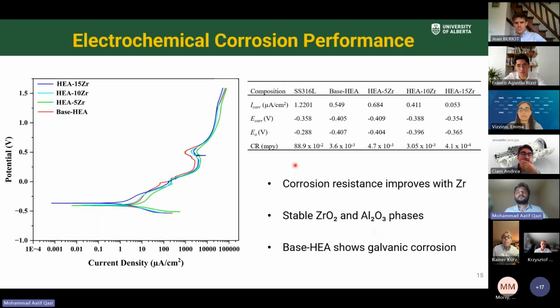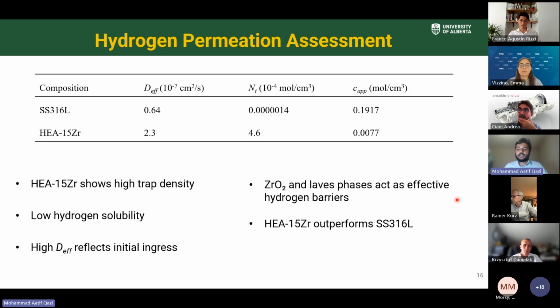Next up, we have the electrochemical corrosion testing, which shows increase in the corrosion resistance as the Zr content in the coating increases because of the formation of stable Al2O3 and ZrO2 phases. And finally, the hydrogen permeation performance assessment of the coating showed initial hydrogen ingress due to high diffusion coefficient, but suppresses the hydrogen movement within the microstructure because of high trap density and low solubility, overall outperforming the substrate SS316.